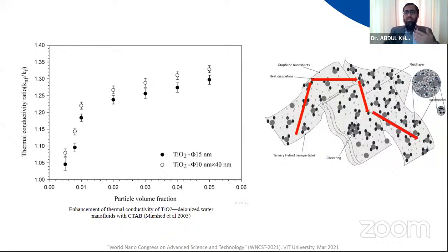What we say is, when you have 2D structures such as what you see on the screen, the conductivity mechanism is clearly established. For example, when 2 or 3 different flakes get in contact in a reaction volume, the percolation effect will become prominent, and the heat transfer path will become more shortened, and the heat transfer rate will also be augmented, increased.